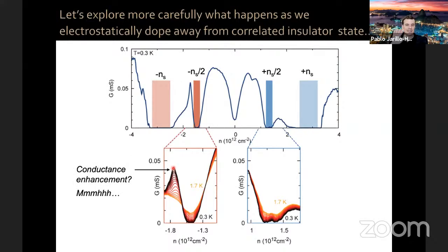Now, these devices we measured in a 2-terminal geometry, meaning we have source and drain electrodes. We apply a voltage and we measure the current. Now, this 2-terminal geometry always adds a series resistance to our device.